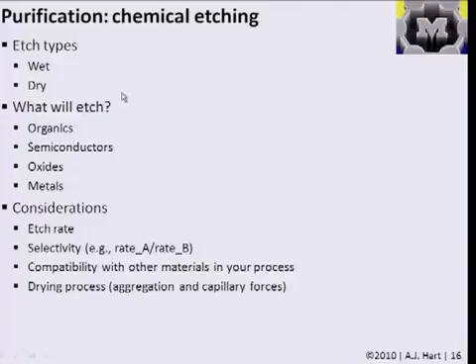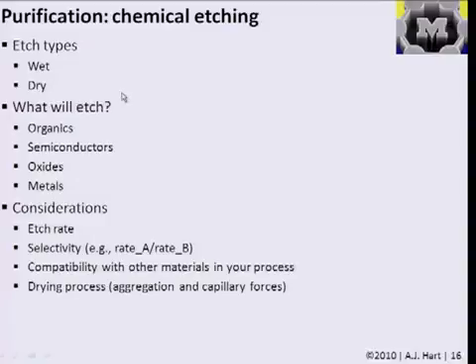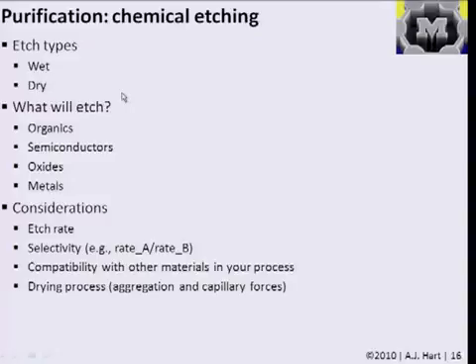Something particularly important for small structures is how you dry the material after a wet etch. Capillary forces get stronger as size decreases. For things like releasing thin films and MEMS, stiction due to capillary forces drawing structures together is a very important problem. At the nanoscale, if you etch a forest of nanotubes in a wet solution, the nanotubes will aggregate together due to capillary forces during drying. Techniques such as critical point drying — also used in MEMS — are useful for preventing undesired aggregation during drying.